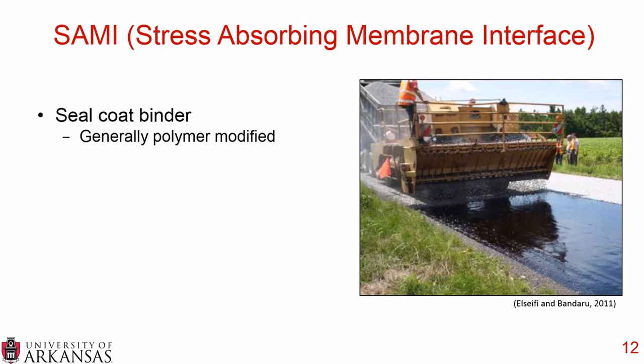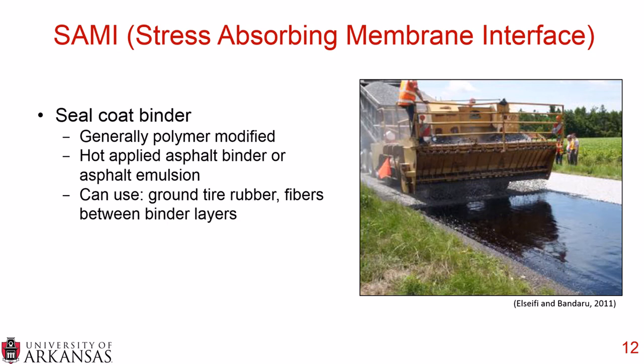Now, SAMIs, stress absorbing membrane interfaces, you generally place some sort of seal coat binder down, and this is generally polymer modified. And as I mentioned, this can be hot applied asphalt binder or it can be asphalt emulsion. And you can use ground tire rubber, you can use SBS polymer, and you can also place fibers in between binder layers. So you can put a thinner layer of either hot applied asphalt binder down or asphalt emulsion, then place some fiber, and then place another layer of asphalt binder or asphalt emulsion. So there's various ways to modify the seal coat binder. You then place your coarse aggregate chips, and essentially this turns into a chip seal.